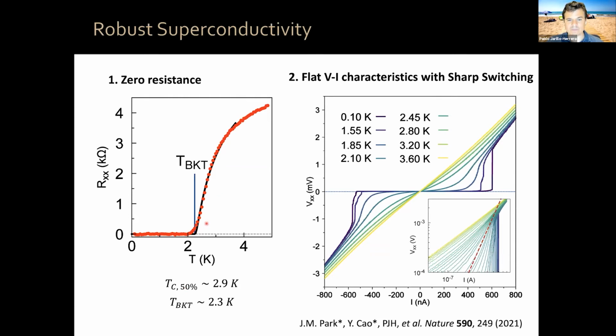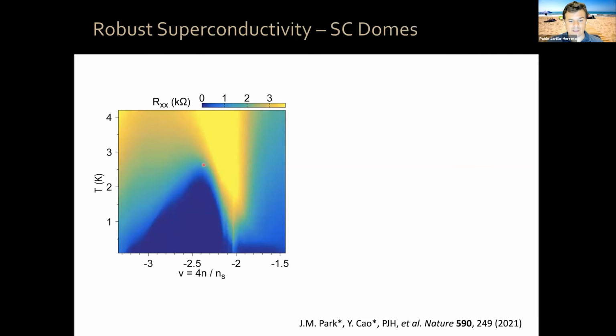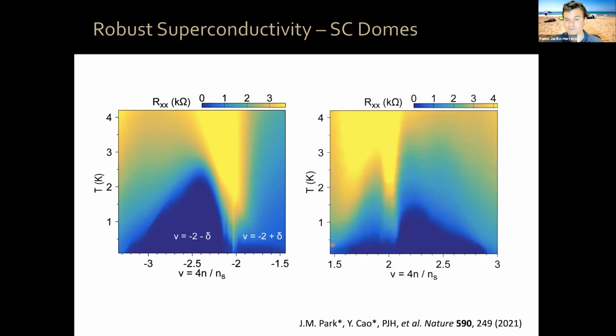Then the system is also an electrically tunable superconductor, similar to magic angle twisted bilayer graphene. If you fill around 2 holes per moiré unit cell, you can fill with extra holes and you have a superconducting dome. You also have a superconducting dome at -2 plus delta, where plus delta means a few electrons with respect to the 2 holes. You can do the same thing around 2 electrons per moiré unit cell, also 2 superconducting domes on this side. We control all of this electronically.